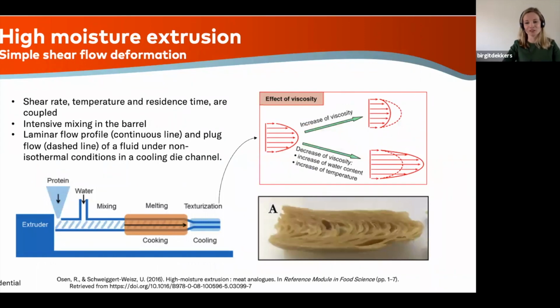I already got the question, can you explain how this is different than extrusion? So one of the aspects which is different from an extruder with shear cell technology is that in an extruder the shear rate, the temperature, and the residence time are always coupled. So as soon as you start to increase the shear rate, the residence time in your extruder typically becomes shorter. And also the temperature is affected if you increase the shear rate.